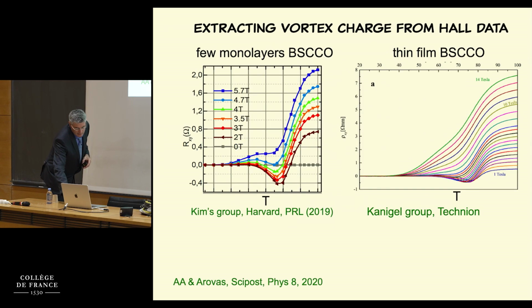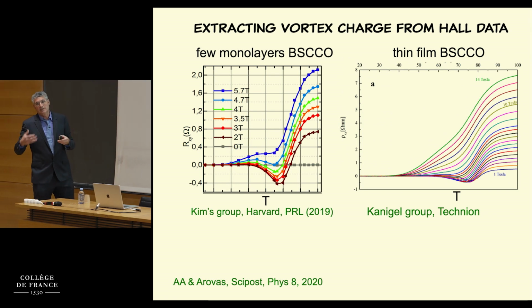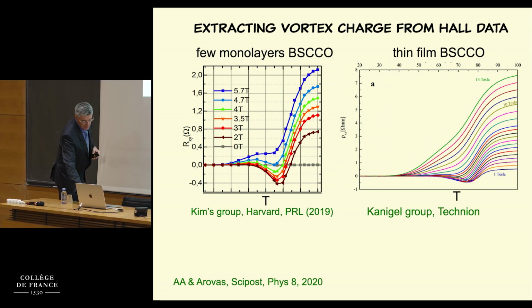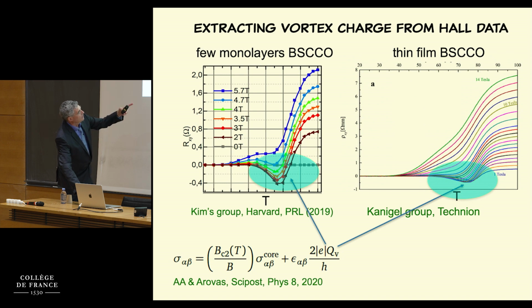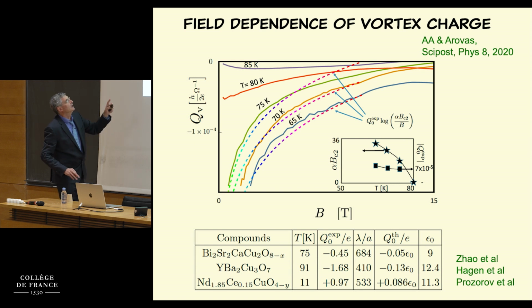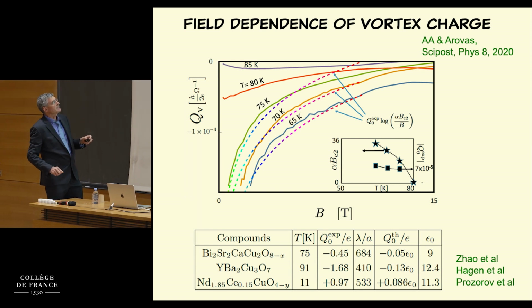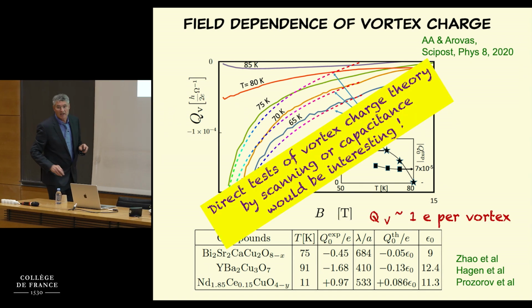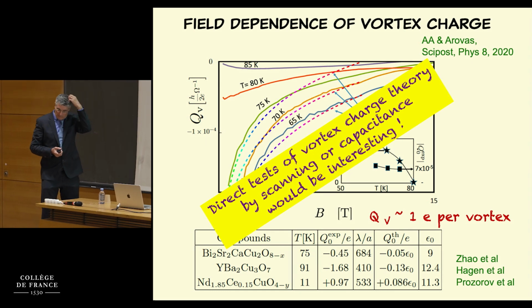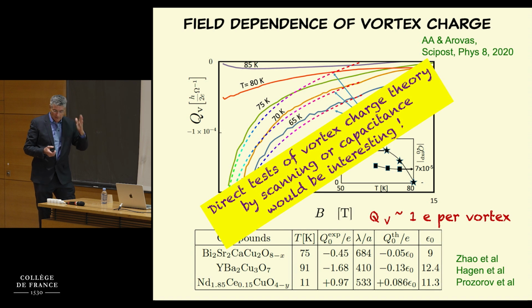And we calculated from the experiment what is the size of the vortex charge that these experiments give. So you have to invert the matrix of rho xx and rho xy to get sigma, and using this expression and subtracting the extrapolated value from the high temperature, we got the vortex charge, and we plotted how it depends on magnetic field, and it depends logarithmically as expected. And the overall magnitude, just for interest, of the vortex charge per layer is about 1 electron per vortex. So 1 electron per vortex is a very small charge, difficult to detect, especially on metals, but hopefully somebody will succeed in doing it.